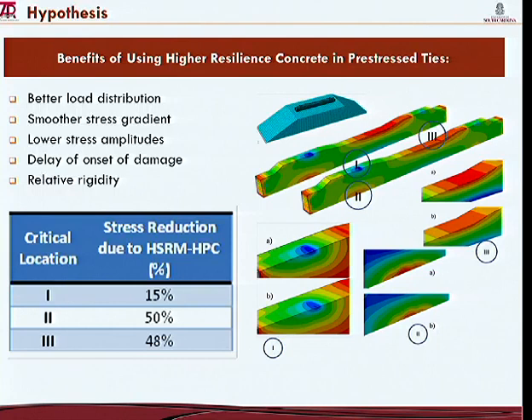So some preliminary studies based on finite element analysis alone show that if we reduce the modulus of elasticity by 50%, then we can reduce the stresses from 15 to close to 50% at different critical locations related to the rail seat, center binding, and under the rail seat at the interface with the ballast.